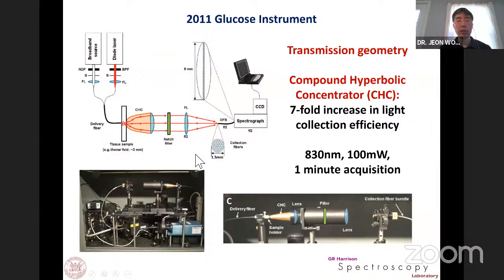This time, instead of a paraboloidal mirror, we used the compound hyperbolic concentrator and compound parabolic concentrator. When the scattered light is coming out of the skin, it spreads all over the 2pi solid angle. But even though we are trying to collect a lot of scattered light, the maximum we can collect is about 20 to 30% using a high NA mirror. If you are using a paraboloidal mirror, then you can collect a little more, but not too much. The compound hyperbolic concentrator converts 2pi solid angle rays into the acceptable angle of the collection fiber, which means that you can effectively collect all the rays from 2pi solid angle.